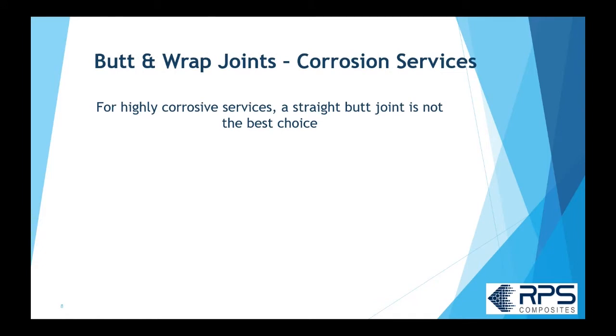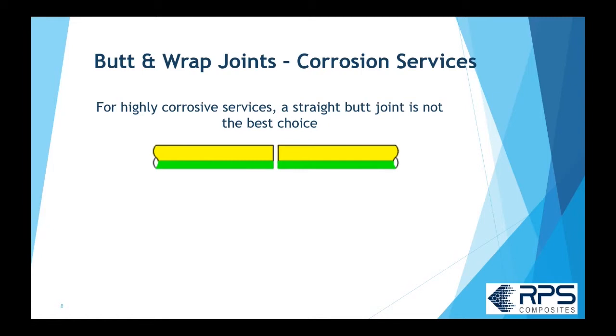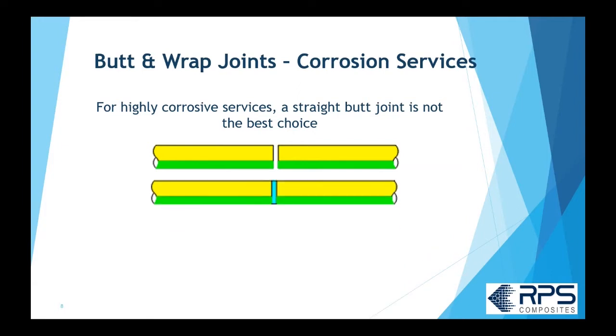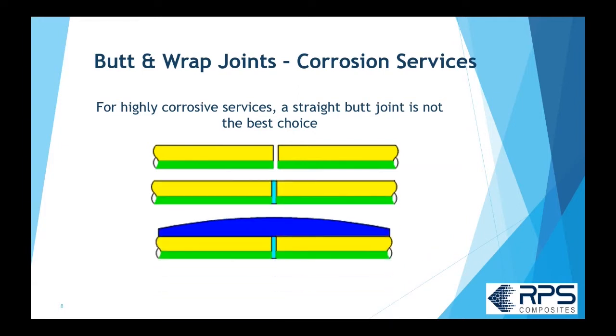When you have a highly corrosive services, a straight butt joint is not actually the best choice to use. And the reason is, I said before, you take your two surfaces, you get them as close as you can, about an eighth of an inch. You put that crevice paste in there and you laminate over top of it. But what can happen is the chemistry, the chemicals inside the pipe can sometimes work their way through that crevice paste if there's little cracks in that crevice paste, because it's essentially unreinforced. It has some milled fibers in it, but that's about it. So if chemicals get through that crevice paste, they can attack the structural layers of the piping or the butt joint itself.